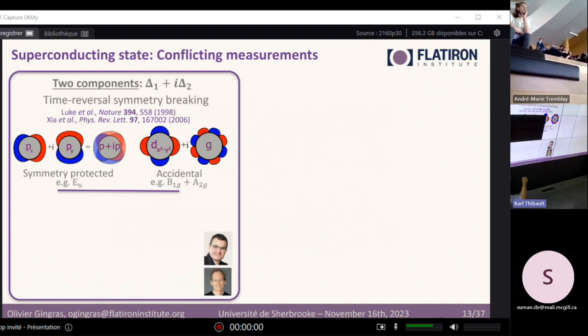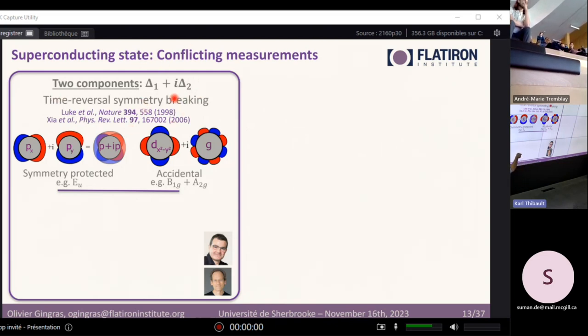Okay, so the two-component nature can be inferred by the fact that the state is believed to break time reversal symmetry. The way this happens is when there are small magnetic fields generated within the samples. And one way to understand this is that you can have chiral states that are generating these small magnetic fields. And to have chiral states in superconductors, usually you need two components in the gap function which are related by a complex phase.